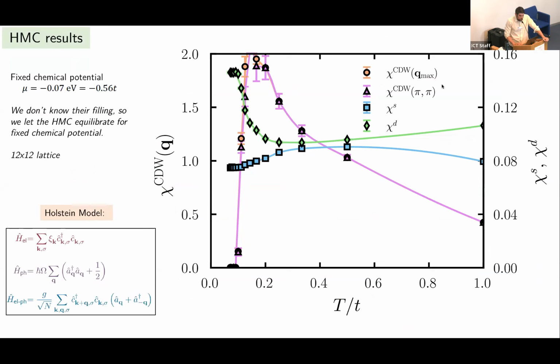So we said, okay, let's assume what they did was correct. Adding this first vertex correction in a self-consistent way gives you potentially unconventional pairing. Do you see this with all of the diagrams included? And how do you include all the diagrams? Well, okay, in an implicit way, a Monte Carlo simulation does this. And so we looked at their parameters, and effectively so far, we don't see any leading D-wave pairing symmetries.